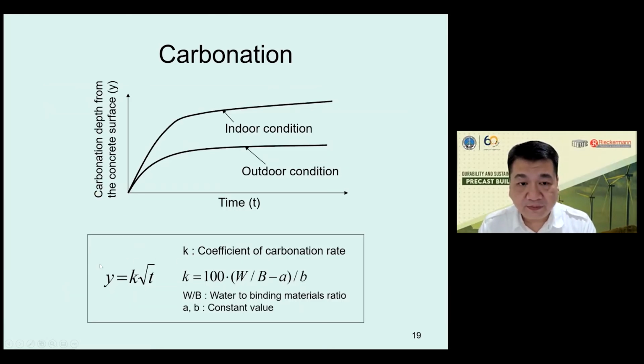So we can calculate the carbonation depth in the concrete with time, depending on the quality of the concrete materials. Normally, the equation will follow this type: Y, meaning the carbonation depth, equals K constant times the square root of time. So we have two conditions, indoor and outdoor, because indoors we have a higher concentration of carbon dioxide. So this is the indoor condition.